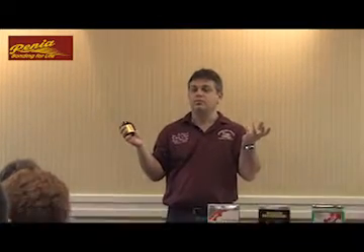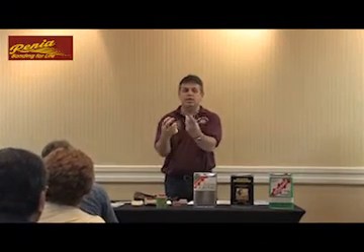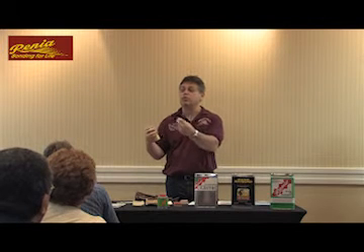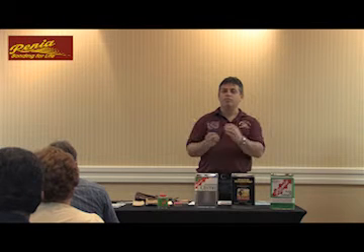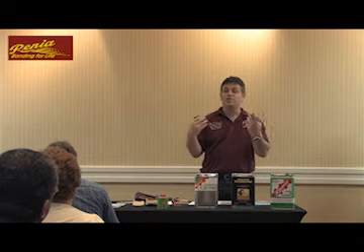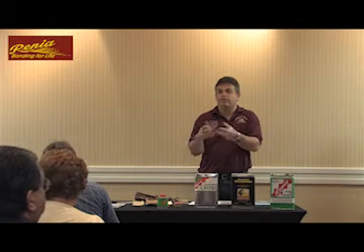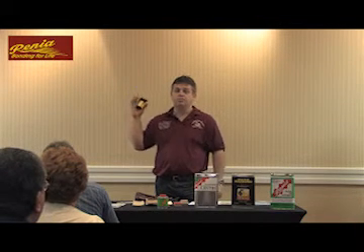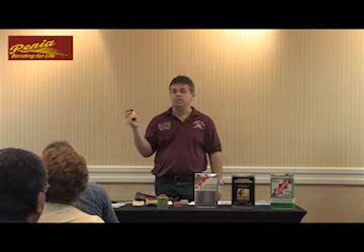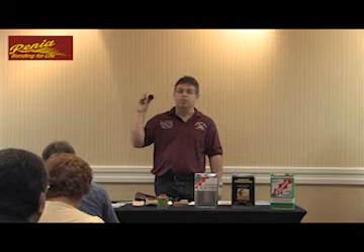Now, if you ever get soft rubber, really soft rubber, sometimes Vibram soles. I don't know if you've ever sanded a Vibram sole and it's got hot and started to peel off a little bit, and then you kind of have to repress it when the glue dries or cools off. Anybody ever noticed anything like that on some of the softer rubber? Because the abrasion is so good that it gets hot when you sand it, and sometimes the glue will reactivate and kind of come apart a little bit. You can even prime that with the yellow primer, and it'll make the strength even 100 times better. You won't even get that separation. So it's very good for soft rubber and then thermoplastic.